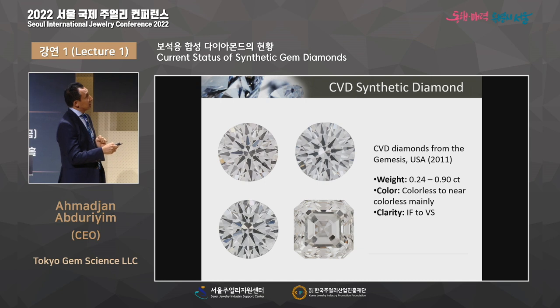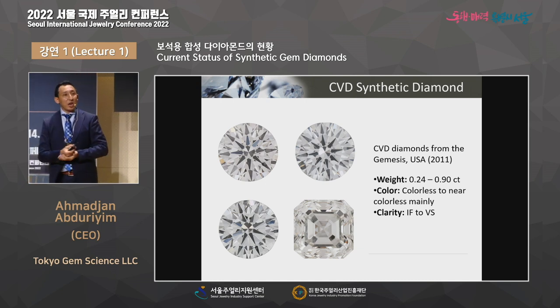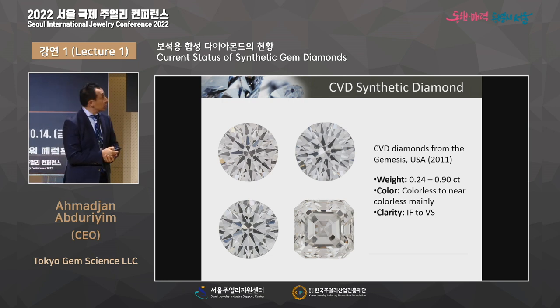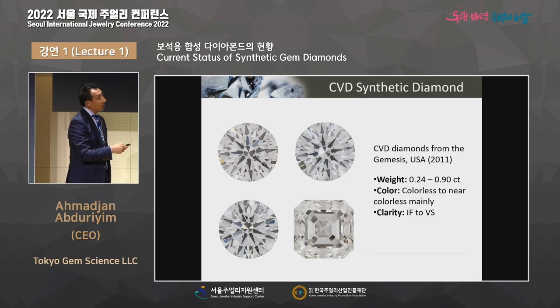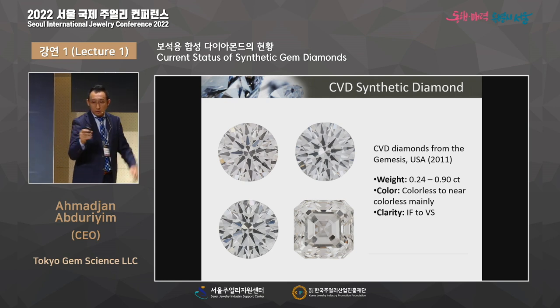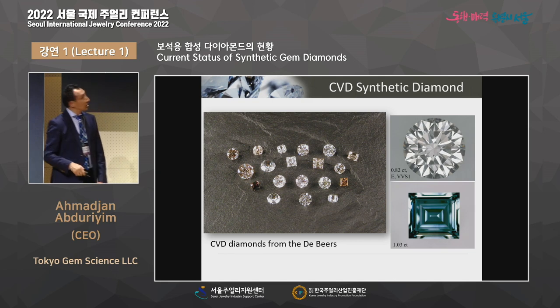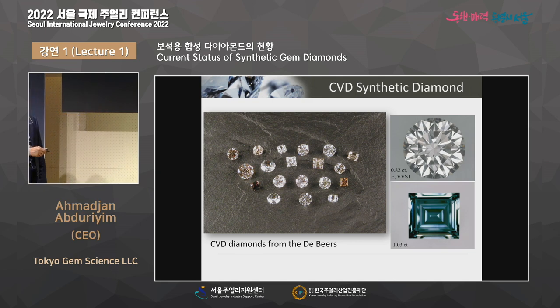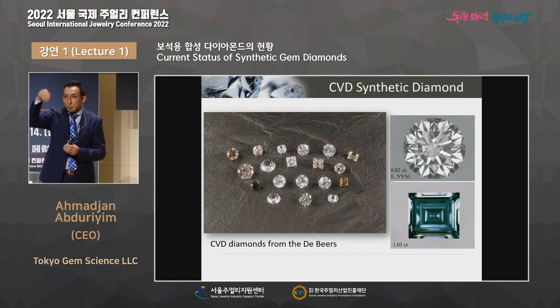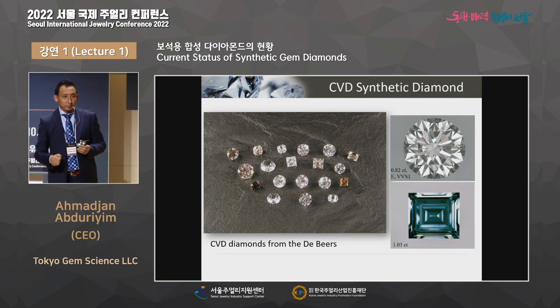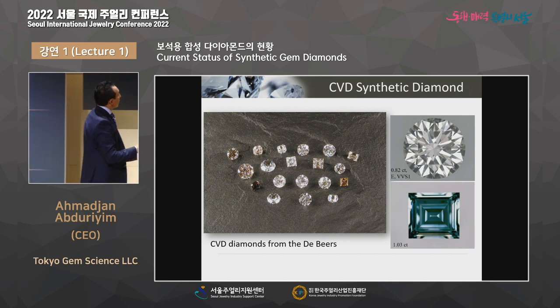And this is Gemesis, another Gemesis. They also create a lot of HPHT synthetic diamond. They started to create the CVD as well. And they make larger ones, after the cut, up to 0.9 carat. It's a little bit bigger. And you see the clarity, IF. Ooh, you cannot find any inclusion inside. Very pure, extremely high technique. And they tried to make blue as well as HPHT. They dope boron inside to make a CVD diamond. So, oh, all colors there. They can start from brown to make colorless, and some yellow or orange.